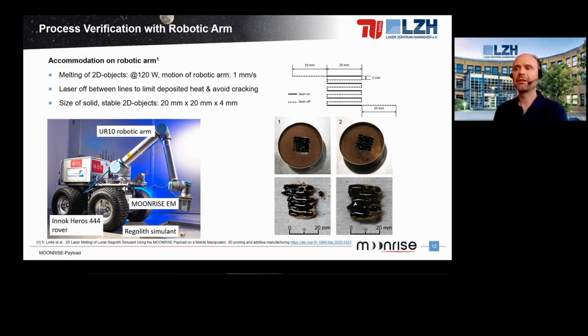The next step was to make larger objects. Therefore, we accommodated our engineering model on a robotic arm. We had a motion speed of 1 millimeter per second at 120 watts of optical power, and we go line by line. In between, we had to switch off the laser to limit the deposited heat and avoid cracking, but we achieved 20 by 20 by 4 millimeter sized solid objects.